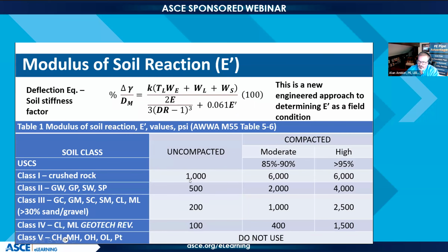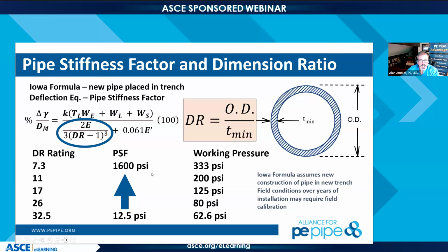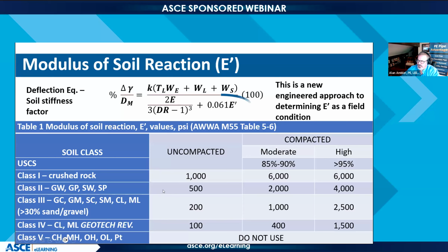Okay. So one of the slides I kind of glossed over here shows us that pipe stiffness factor. So this does work with the exact soil stiffness that Brian was just discussing. And we'll see a fairly dramatic difference between a DR 7.3 and that DR 32.5. So when we start to look at that thinner wall pipe that's outside of that design window we were in reference to earlier, then yes, that engineered backfill gets significantly more important to us as we continue through it.